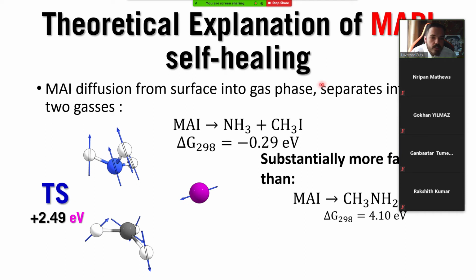So what do we do? Well, simple. We just calculated the transition state barriers of creating these gaseous products. The barrier to make ammonia and methyl iodide is quite low, 2.5. And it's also a favorable reaction. You actually get energy out as you make it. Then we also have, of course, the reaction that creates hydroiodic acid. It's not as favorable, but when it becomes aqueous, so under exposure to water, it of course becomes more favorable. So this reaction is probably a very large issue for perovskites that are exposed to water.